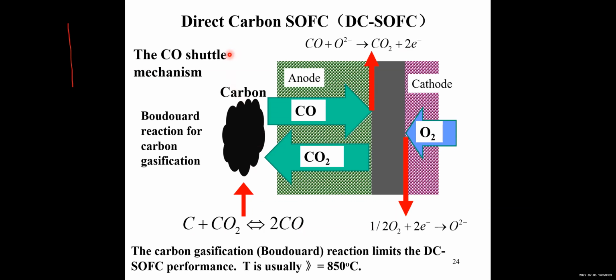However, the fuel cell performance for this type of fuel cell highly depends on the carbon gasification, because this reaction determines the amount of carbon monoxide to be produced, and CO is the actual fuel for power generation. Because this reaction is relatively slow, in order to achieve a good fuel cell performance, normally we need to maintain the fuel cell at a pretty high temperature, for example, 850 degrees Celsius. This is actually not very good, because if the temperature is too high, this will cause some durability issues. The sintering of the anode particles will be significant, and the thermal management will be complicated. So in the past few years, a lot of research work has been done to decrease the operating temperature from 850 degrees Celsius down to 750 degrees Celsius, but actually it's not very successful.